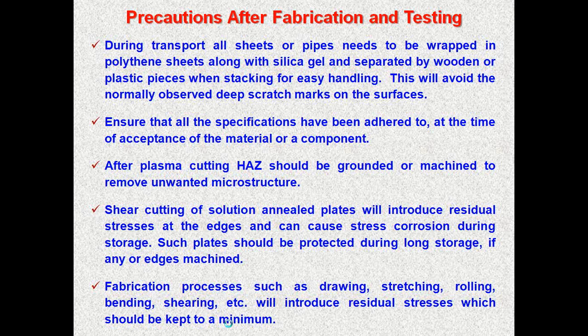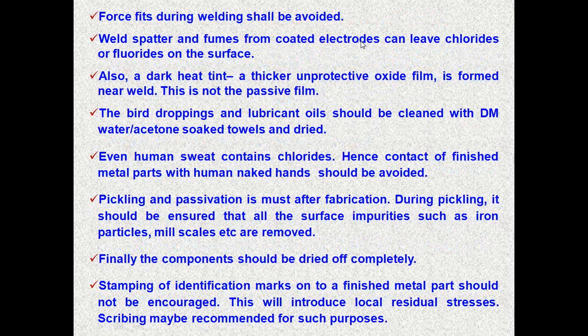Arc strikes and pits during welding shall be avoided. Weld spatter and fumes from coated electrodes can leave fluorides or chlorides and should be avoided. Dark heat tint which is present on the welded surface is an unprotective oxide film. This should be removed by pickling and passivation.